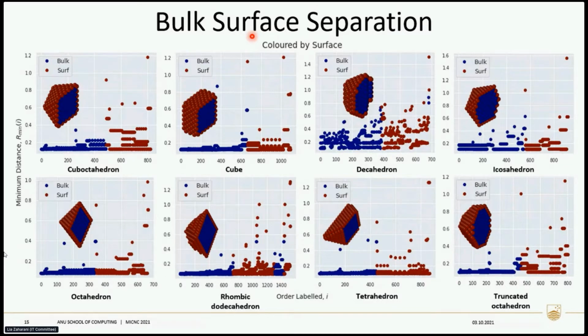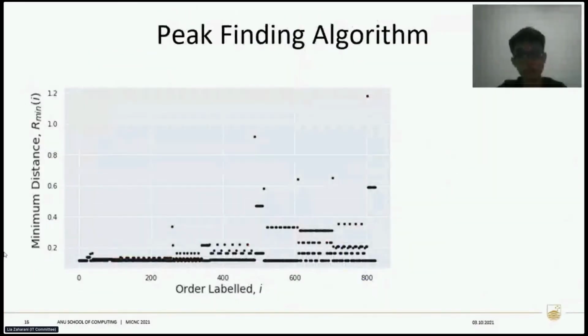You might also have noticed the little peaks in between the bulk and surface atoms. They indicate that there are subclusters within surface and bulk clusters. To find these clusters, we need to label an atom in each of them and rerun ILS. But to do that, we need to first identify these peaks. So if we were to analyze these ILS distance plots in bulk, an automated peak finding algorithm is necessary.